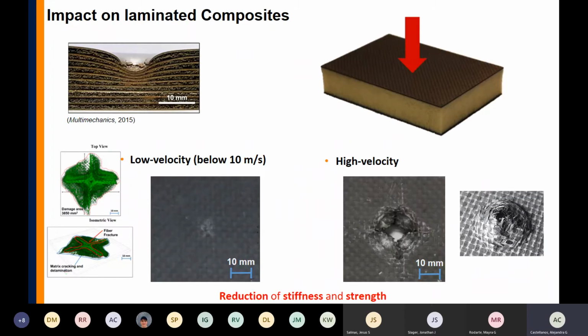As I was explaining before, this resin-rich region between each of the layers of your composite is very susceptible to damage. And just so you have an idea of why, usually the layers of the fibers have a Young's modulus of 125 gigapascal, but in this resin-rich region the Young's modulus is 3.5. So it's really small. That difference between the Young's moduli makes all the damage start in the resin-rich region. One of the loading cases that we investigate, and which is still a challenge, is impact on laminated composites.